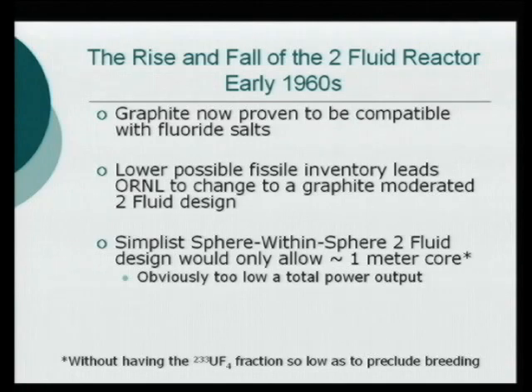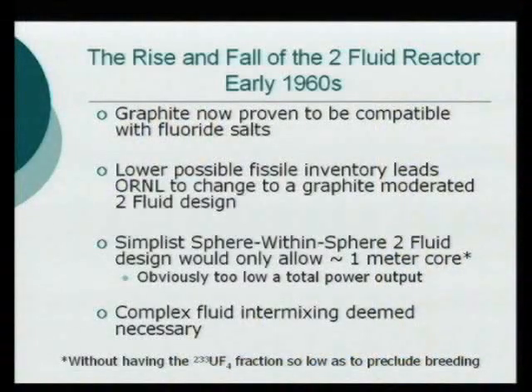Now, the simplest way you might imagine building this is a central core that just has the fuel salt surrounded by a core that has the blanket salt. The problem with that, though, is the critical radius of that inner core would just be too small. It would be on the order of about a meter with the concentrations of fissile that we would put in these salts. That's just too small, not enough volume to have a power-producing volume. So Oak Ridge's solution was, well, we're going to have to mix these salts, not together, but have two salts in the core separated by plumbing, graphite plumbing.